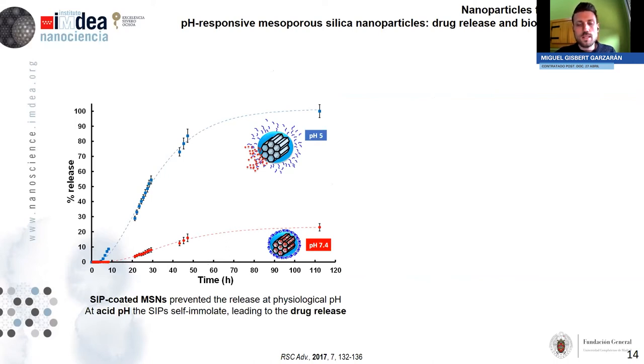So to answer the question, we took our nanoparticles and we placed them in two different solutions, one at pH 7.4, which could be that of the pH of the bloodstream, and another one at pH 5, which would be the pH of the lysosomes. And as you can see in the graph, it is clear that there is a huge difference in the release at both pHs. And this can be understood as that at physiological pH, the self-immolative polymer